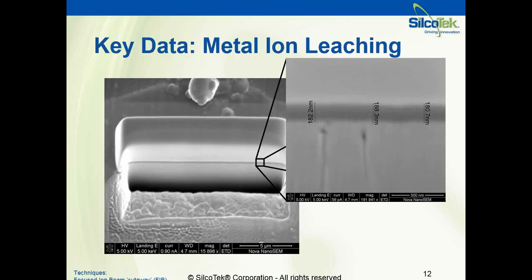So here you can see an ion beam image of a cutaway that we have here, and you can see in the blown up image on the right that dark layer is the solid barrier between the substrate, which is on the bottom, and of course the air on top. So you can even see at this level of magnification that in the bare substrate there are defects. You can see the two cracks or defects in the stainless steel. The layer on top of that steel is the coating, and you can see that there is in this case a roughly 180 to 190 nanometer barrier between the environment and the substrate. So it's very clear that the coating is uniform and complete across the steel surface.